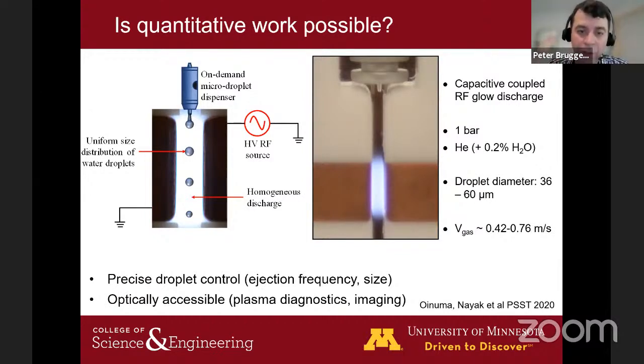And so we wanted to link, and I think that was probably for the first time, plasma kinetics and chemistry in the gas phase to whatever we're doing in the liquid. So we are sending here, and I kind of like this experiment, small droplets going through a homogeneous plasma. We apply our laser diagnostics on the plasma. We know OH radicals, for example, are the dominant species here. And then we can load the droplet with some species. We can collect them. We can see what kind of reactions happen, or quantify the reactions in the liquid phase. And we can try to make a model to bridge these two. So we've been doing that.